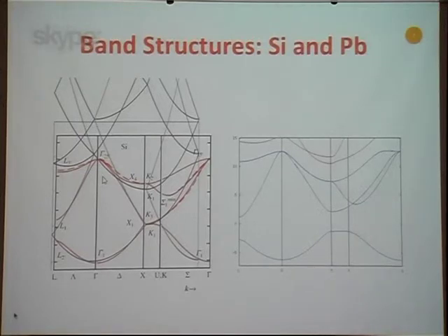You can actually reproduce perfectly the experimental band structure of silicon, both the valence and the conduction, just by perturbing a free electron gas with very weak periodic terms, and you just need typically 3 numbers, that is the 3 components that correspond to the longer wavelengths of the reciprocal lattice, to actually reproduce the band structure.